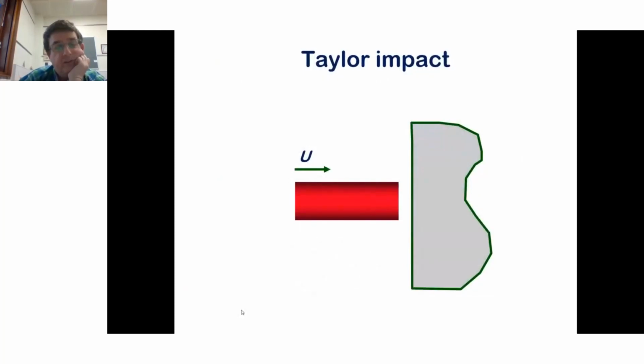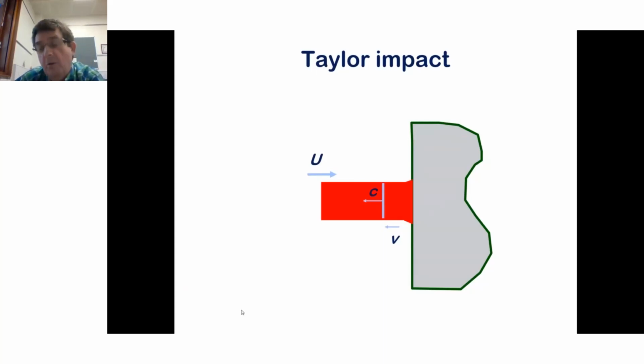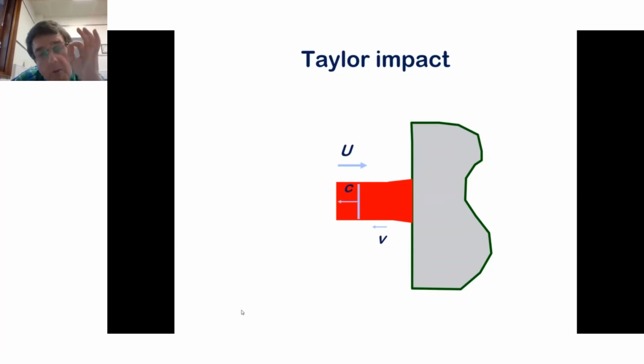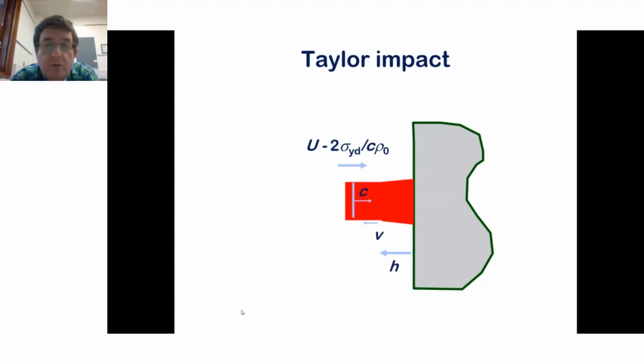And what we're doing, we're firing a rod at velocity u at the surface of a target. It's got an initial length of rod, L0. We send an elastic wave, which moves quickly through the material, and we've got a slower moving plastic or deformation wave behind it, moving at a velocity v. That elastic wave reaches the rear interface of the rod, reaches the back of the rod, and is reflected. Now, I mentioned impedance differences and change at interfaces. You look at that and consider it and think about it. What is the change? Well, the rod is slowed down, and the amount it's slowed down is twice the stress associated with the elastic limit, the yield stress, divided by the wave speed in the rod and the density of the rod. So that simple equation, the simple John Hopkinson style equation, is useful in describing this dynamic event.